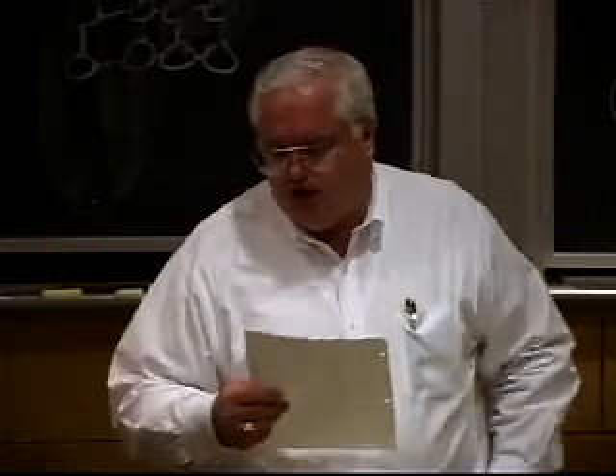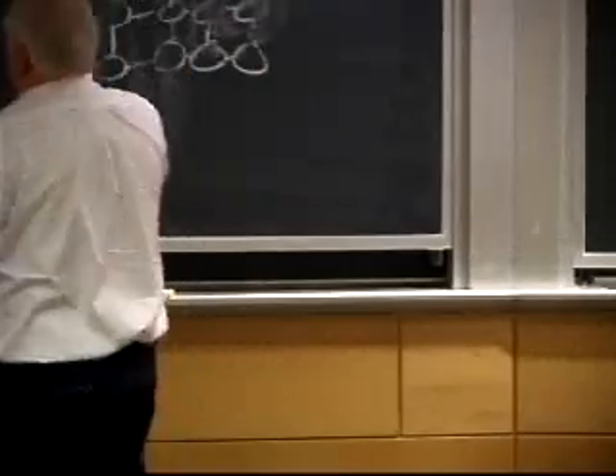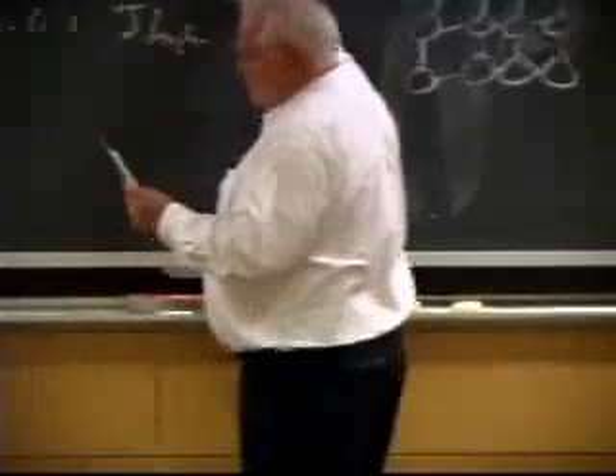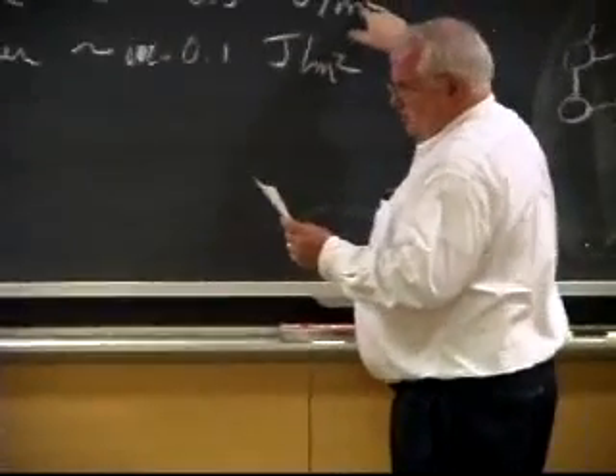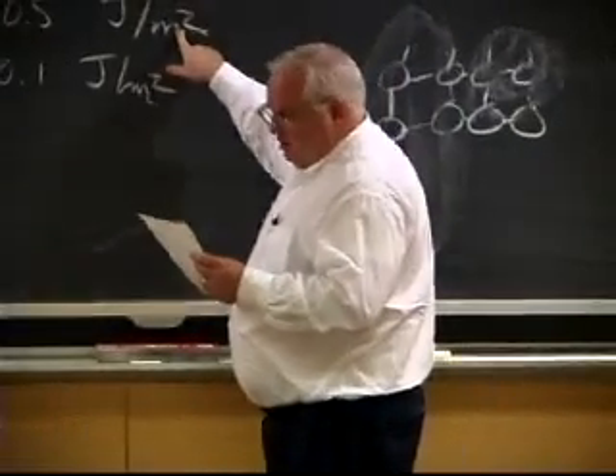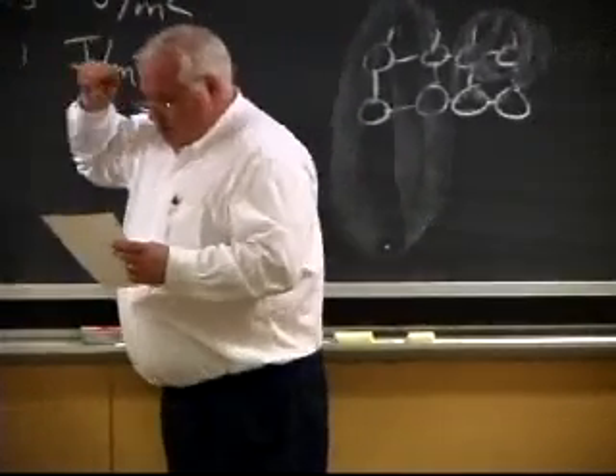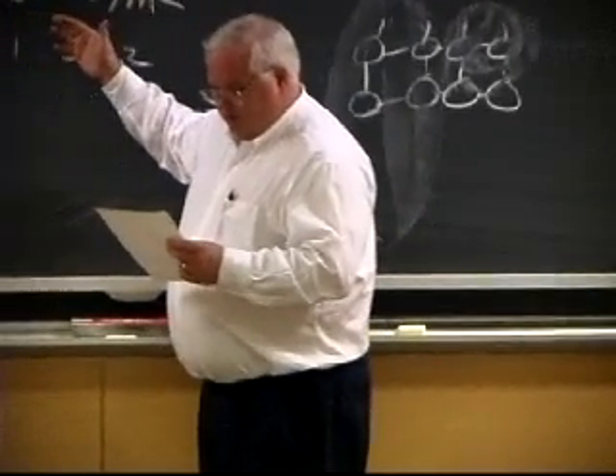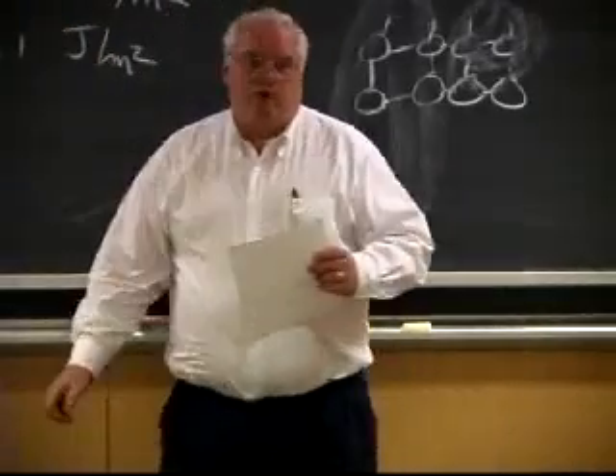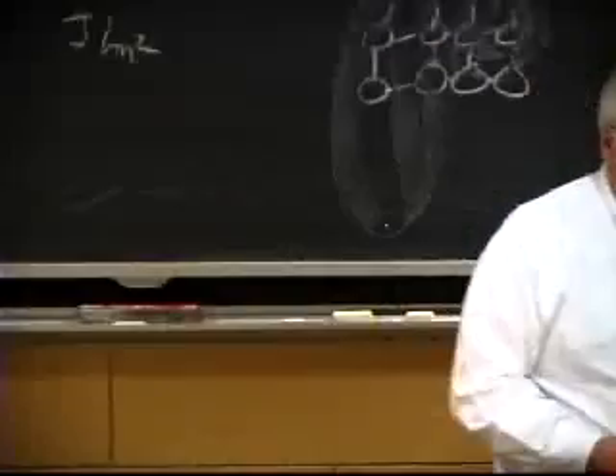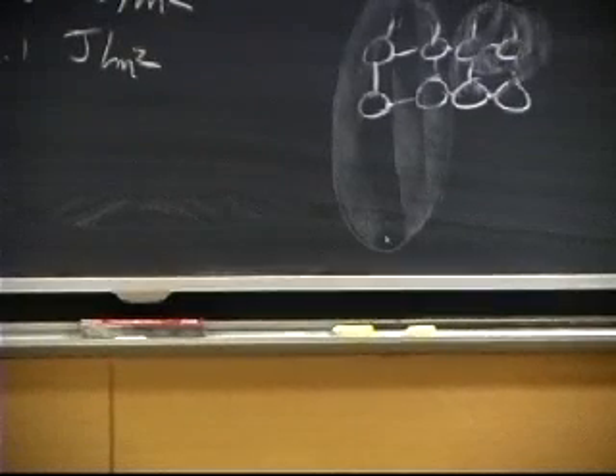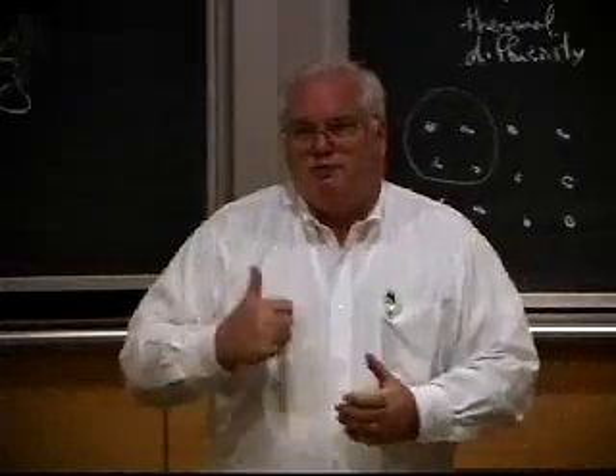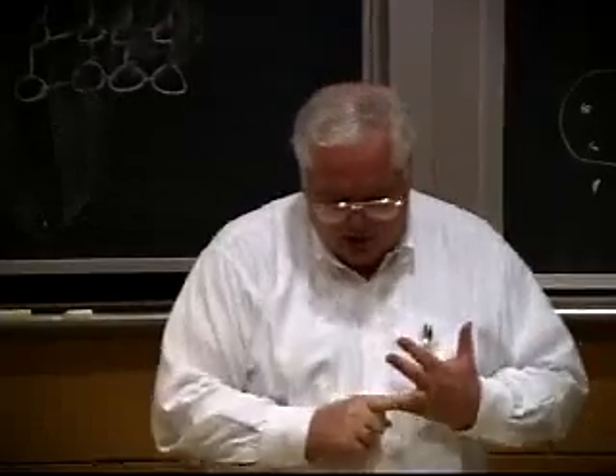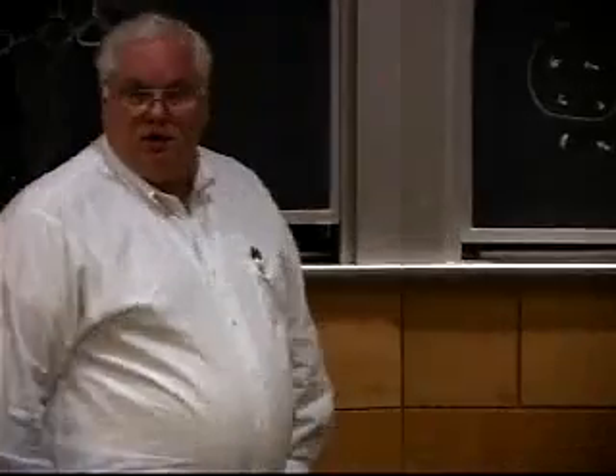Copper has got surface energy of 1.4 joules. If I look on here, aluminum oxide solid has 900. Now it turns out aluminum oxide is a covalently bonded solid, and it's on the high side, so I could have given you a range on this. But let's see, calcium chloride is 0.45. So it varies by a factor of 2 within a given classification typically, but those are the kind of orders of magnitude. That becomes important both in adhesive bonding and also in soldering and brazing, is what the surface energies are. Any questions?